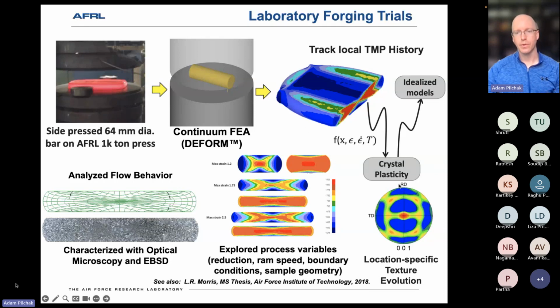The continuum analysis is useful, but we also wanted to couple that with crystal plasticity to see if we could predict the formation of this rotated cube texture component. There we used the viscoplastic self-consistent code, also from Los Alamos, in an uncoupled fashion. I would export the thermomechanical history from specific points within the forging, and then use that to drive the crystal plasticity model. We got a little fancier than that, and I'll touch on it in a second. We tried to be clever about how we introduced the temperature effects.